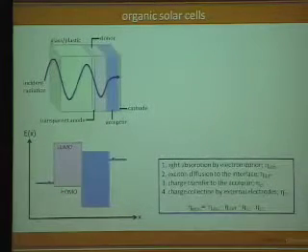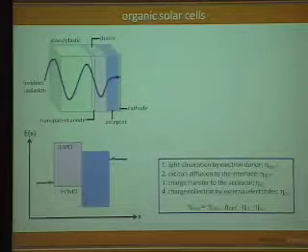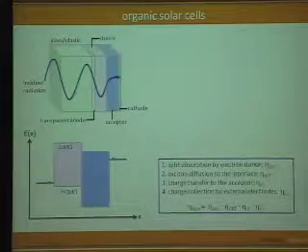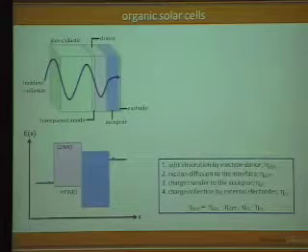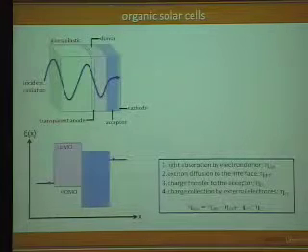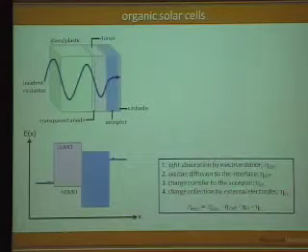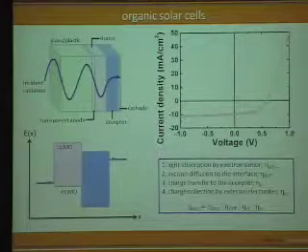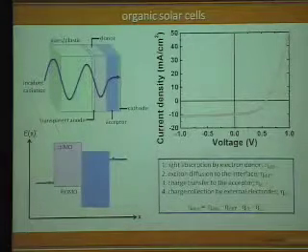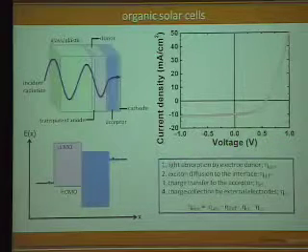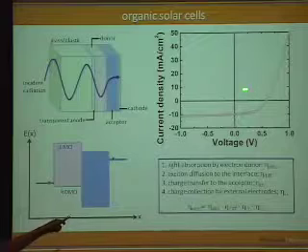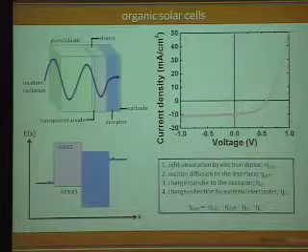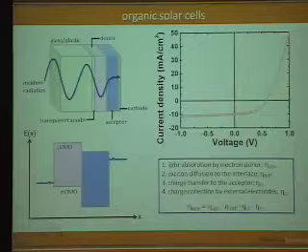Solar cells are inherently not very efficient devices, and organic solar cells especially are not very efficient. The highest efficiency reported is about 6%. The efficiency of a device is a compound of all these different efficiencies — if one single step is not efficient, that propagates onwards. To characterize these devices, you plot current density as a function of voltage and get a diode curve; it's the area below the zero line that gives you device efficiency. The bigger the area, the better your devices.